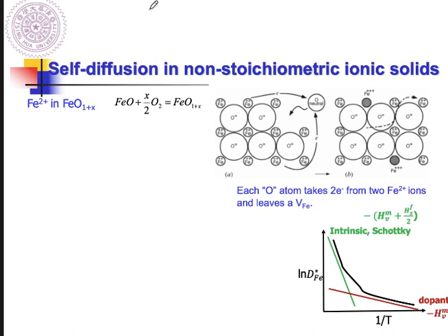For this case, the iron has two positive charge, right? So what does non-stoichiometry mean? It means that iron ions with three positive charge also coexist in this ionic material. So we have iron with two different charges. Under this situation, we call it a non-stoichiometry effect.